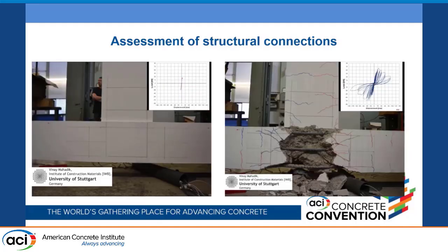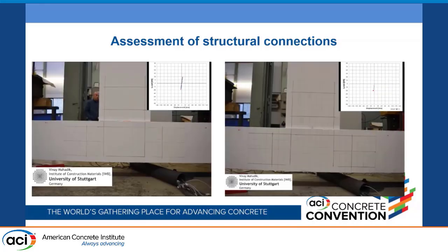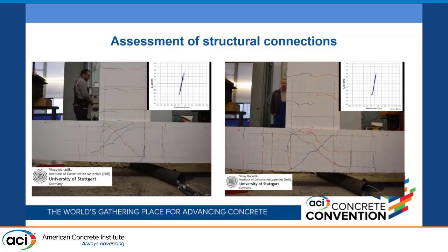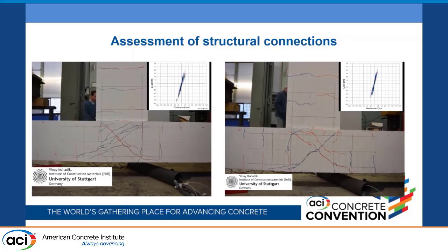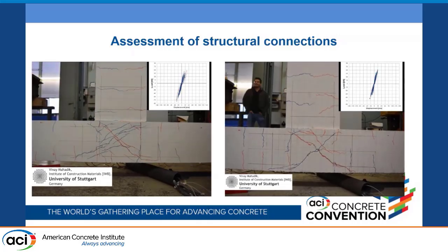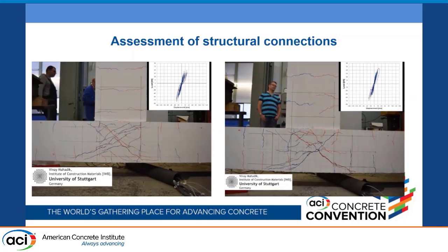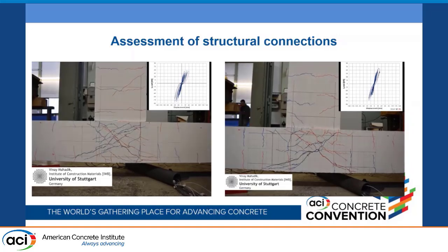We also did similar tests on beam column joints. So once again, let me see. Yeah, this is for cast-in, and this one is for post-installed. And once again, we see that in case of beam column joint, eventually it was failing by joint shear failure in both cases, but the performance of the post-installed one was quite similar to the cast-in with hook.